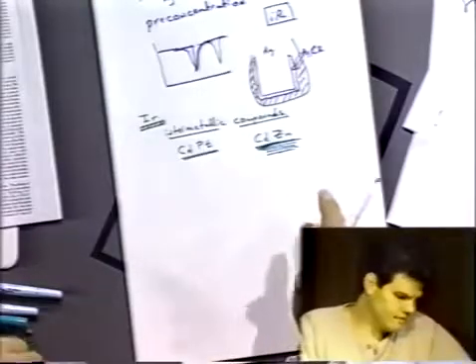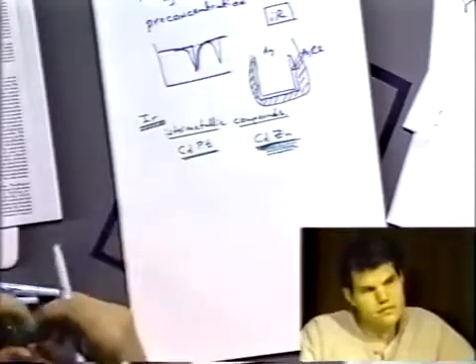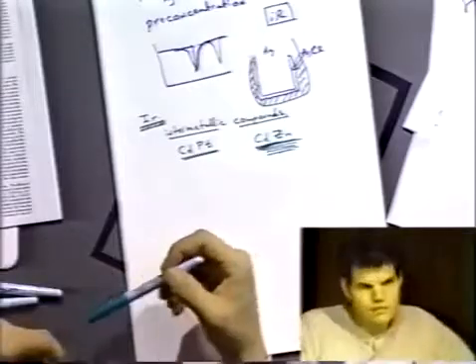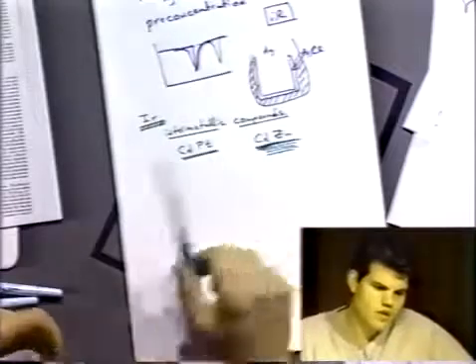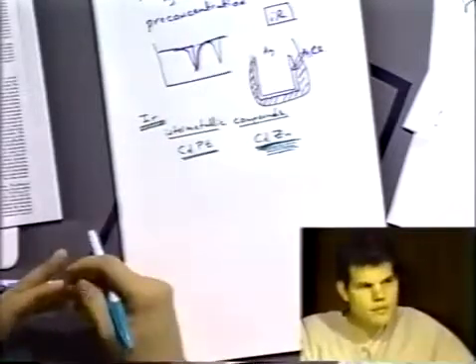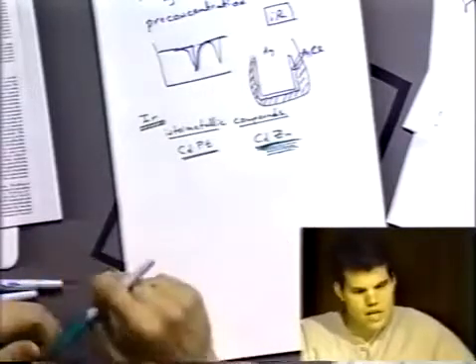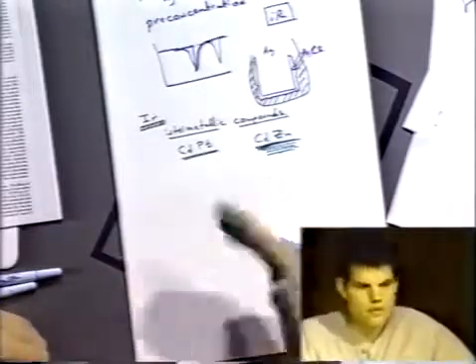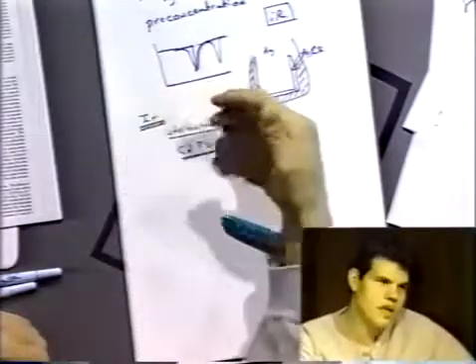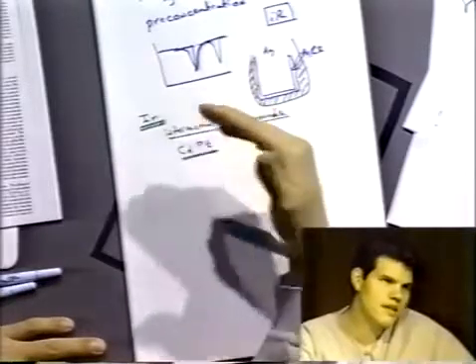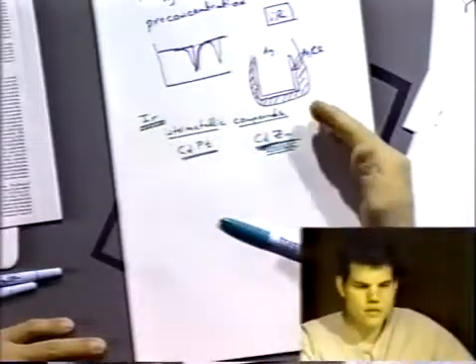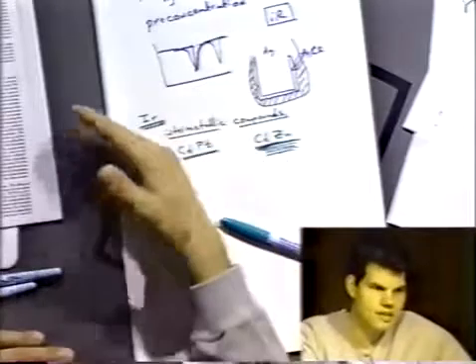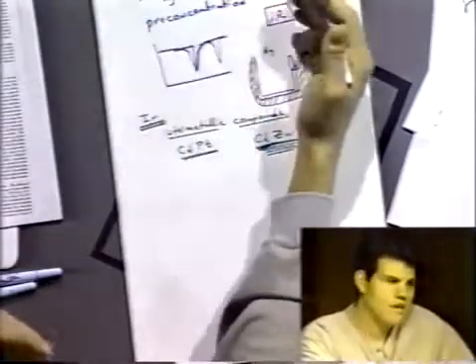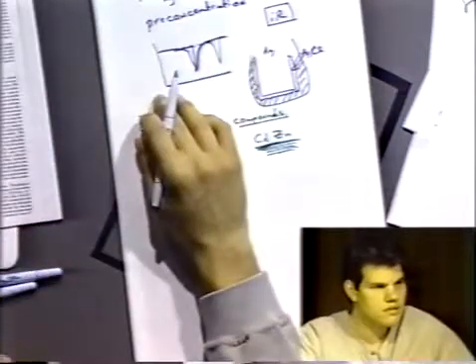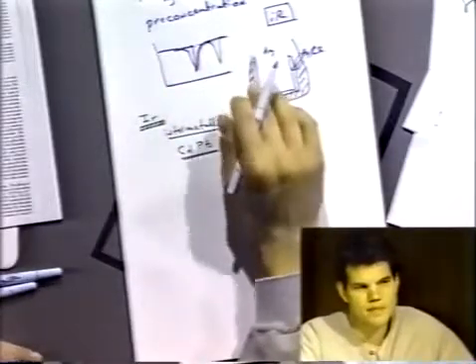Is this method specific for certain ions, or can it determine different oxidation states for the same metal, like iron(II), iron(III), in stripping voltammetry? Yeah. No, once you reduce the metal into the material, you're forming the metal in its metallic state. So you can't directly see the difference in the metal species. What you'd have to do is some preliminary steps to remove one form of the species and then do the other one, or make it so that, for example, one of the ions can't be reduced onto the mercury by setting the initial reduction potential. You can make sure that only one form of the ion would be reduced, and then you could strip that out, and then you could do it again with, say, both ions reduced, and then strip that out, and then you can see by difference what the things were. Iron's not a good example because it doesn't form a good amalgam with mercury, but that would be the idea.